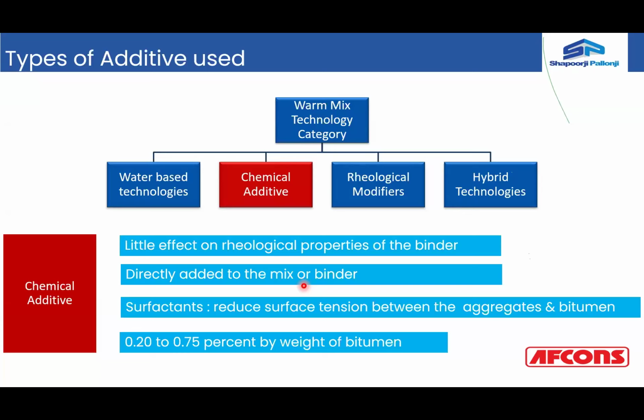They can be added directly to the mix or the binder, but generally we go for the addition in the binder itself. There are surfactants which reduce the surface tension between the aggregates and the bitumen, added at 0.2 to 0.75% by weight. The doses of Evotherm range between 0.2 and 0.75 depending upon the type of advantage you normally want to take. Generally, if you go for a 0.4 dose of these additives, you can reduce your production temperature by 30 degrees, and you can reduce your compaction envelope by 20 to 25 degrees.